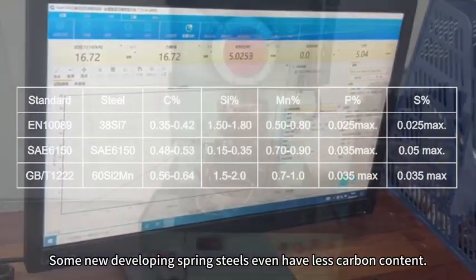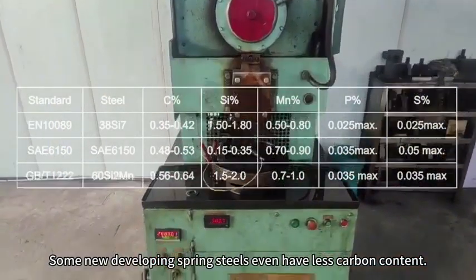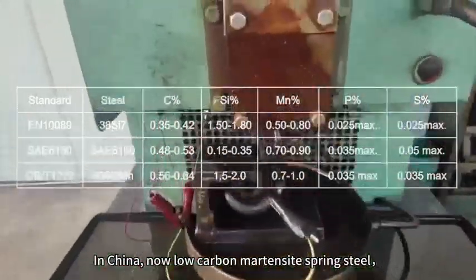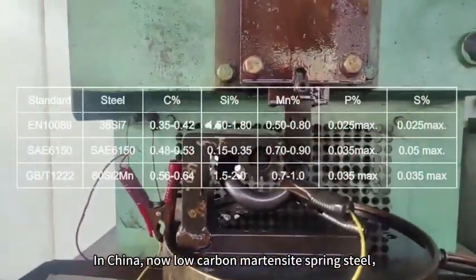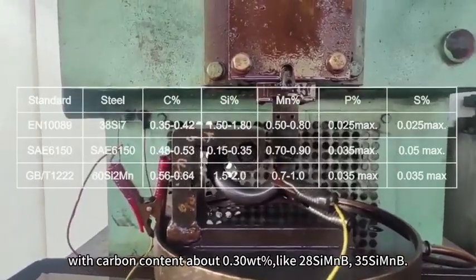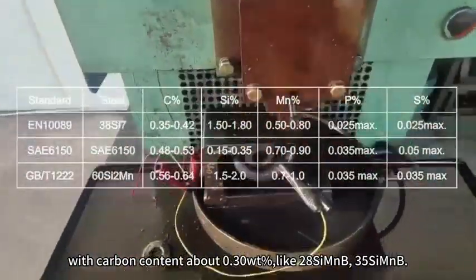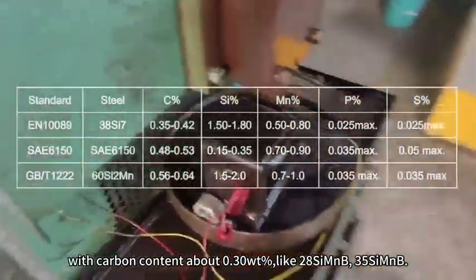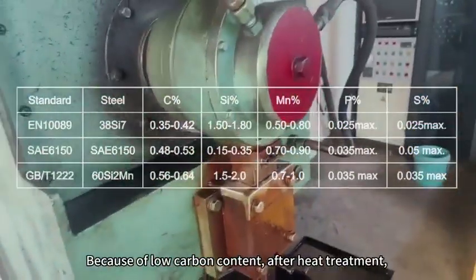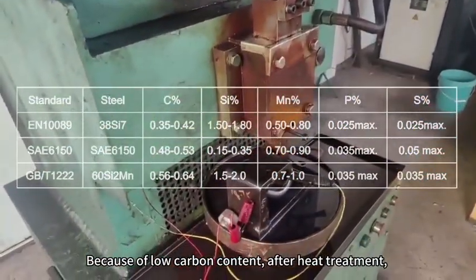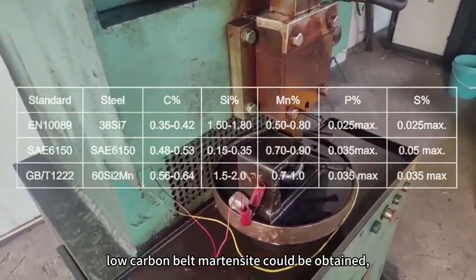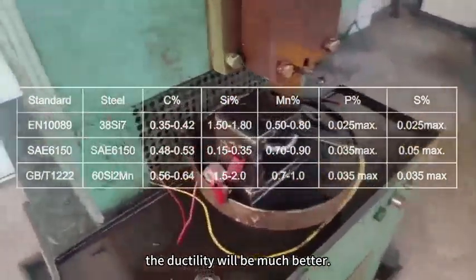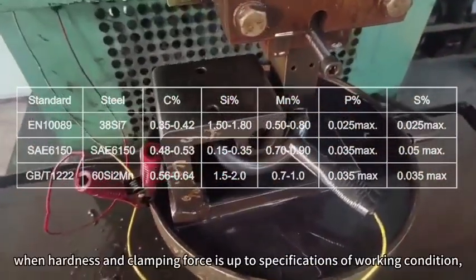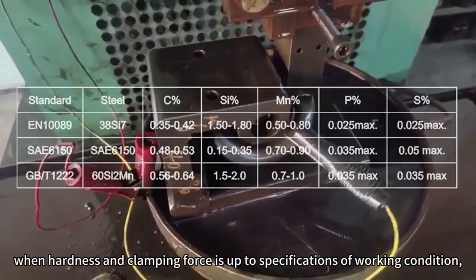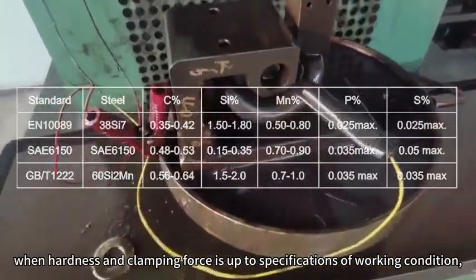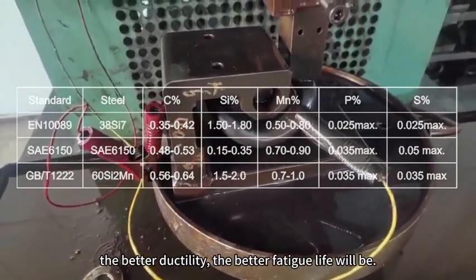Some newly developed spring steels have even less carbon. In China, there is now low carbon martensite spring steel with carbon content of about 0.30 Wt%, like 28SiMnB and 35SiMnB. Because of the low carbon content, after heat treatment, low carbon lath martensite can be obtained. The ductility will be much better. For rail clips, when hardness and clamping force reach the specifications of the working condition, the better the ductility, the better the fatigue life will be.